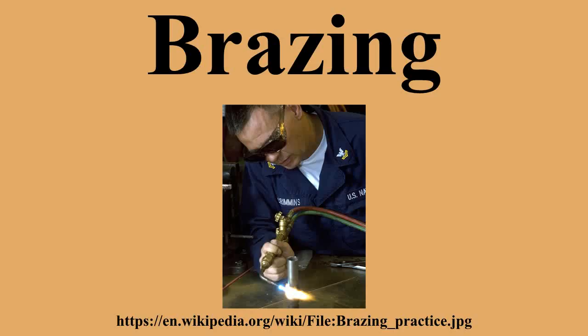Combusted fuel gas: 70 to 71% N2, 5 to 6% CO2, 9 to 10% CO, 14 to 15% H2. For copper, silver, copper-phosphorus and copper-zinc filler metals. For brazing copper, brass, nickel alloys, Monel, and medium carbon steels.